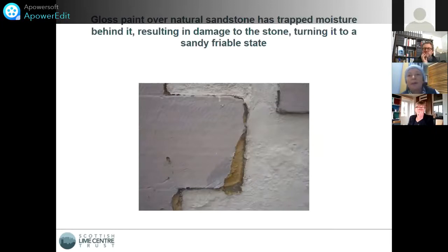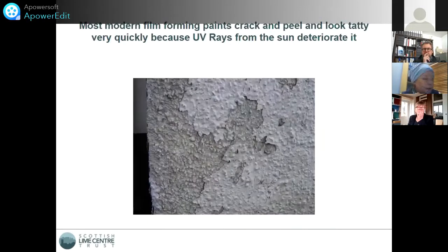Stacey will go into this in a bit more detail, but using impervious gloss paints over natural sandstone in this case has trapped the moisture behind it, resulting in damage to the stone, turning it to a very sandy, friable state. And because most modern film forming paints crack and peel and look tatty very quickly, because the UV rays from the sun are its main deteriorating factor, whereas lime washed finishes will weather and age more gracefully.